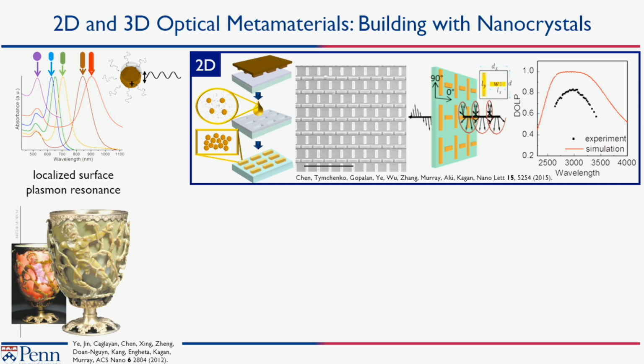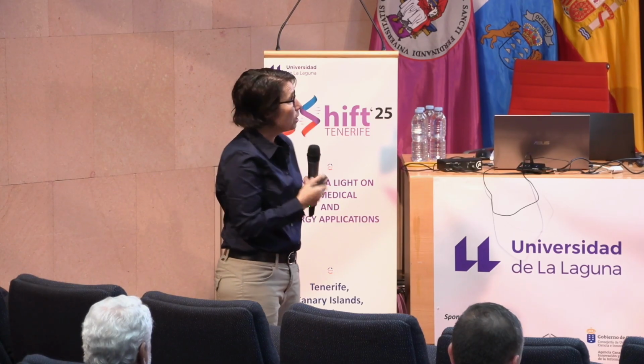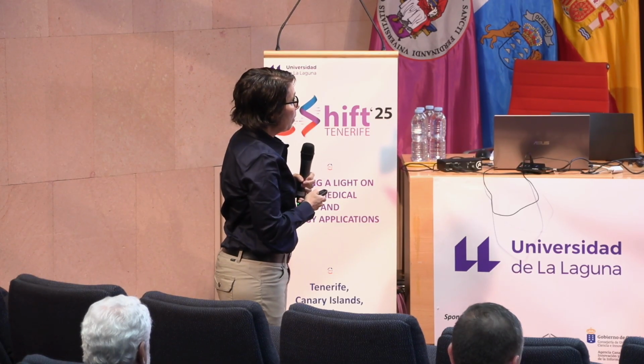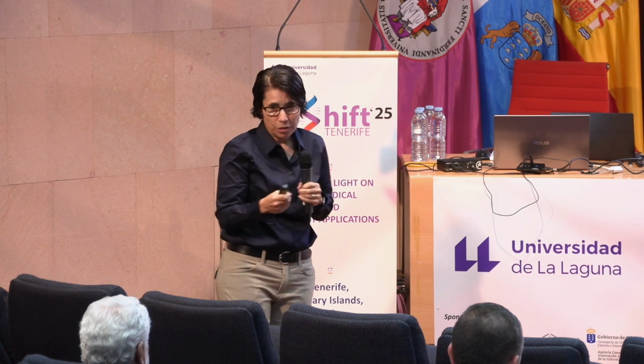And you can then deposit the nanocrystals in solution, as colloids. So we cast them on the surface, often just by using spin coating. And then once you do that, you can just immerse it into this solution of this ligand for something like 30 seconds. And what happens is those particles come together, they become good metals, and then the characteristics that you get depend on the geometry of the printed structure, no longer individual nanocrystals.